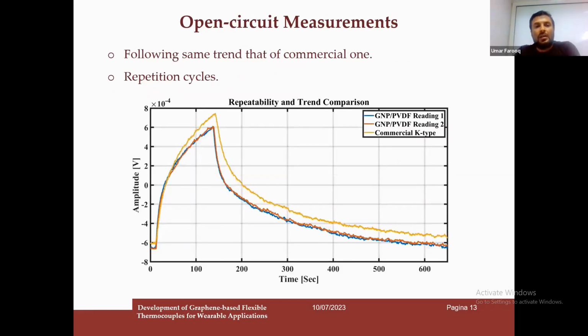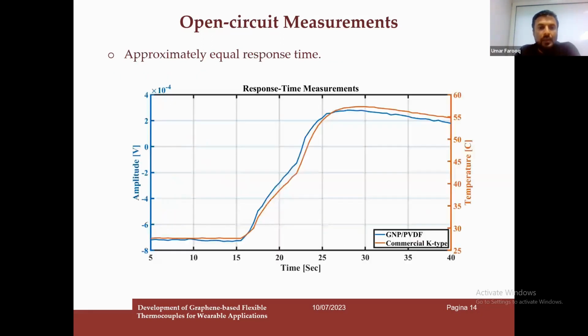Secondly, we observed that the trend in the time response was similar to the commercial thermocouple, and in the repetition cycle it returns exactly to the point where it started from; we took two measurements to see the repetition cycle. And here is the time response of both the commercial sensor and our sensor, and they are following approximately the same response time. So this shows that it is close enough to use this type of sensor.